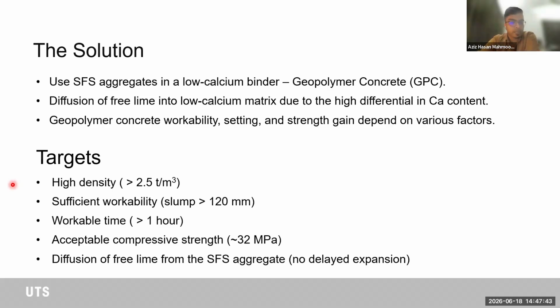So we were targeting high density because of what came out of UNSW Water Research Lab, where they have demonstrated that even a little bit of increase in your density can result in a very stable breakwater unit formation. Now, the other aspects were material based. So we were trying to have sufficient workability, so a slump of over 120 millimeter.